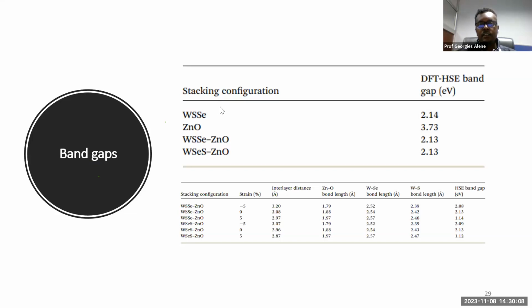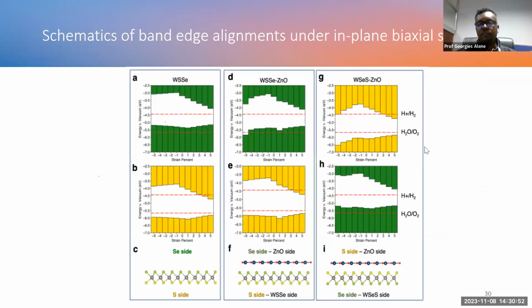This is the different stacking configuration, the two stacking configurations, and the two constituting materials, WSSe and zinc oxide. And we have also calculated the band gap values for this. And as you can see, actually, the band gap value is determined by the WSSe, which is similar to the WSSe. As I mentioned before, when we see the conduction band minimum and valence band maximum, I said that it is contributed by the WSSe. So on the band gap value, this zinc oxide has no significant effect.